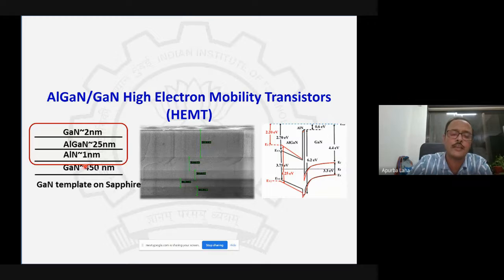If you look at this part of the device, which is primarily the active part, it consists of gallium nitride, then a very thin layer, about 1 nanometer of aluminum nitride, which may not be necessary at this point, and then 25 nanometers of aluminum gallium nitride. And what you get is a beautiful device. This is very unique. You don't get this in any other materials. You don't have to dope anything. You get a transistor.